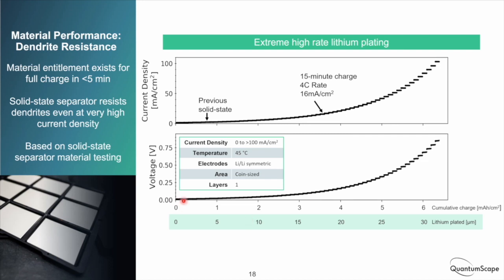And so this is showing the corresponding voltage that develops across this lithium-lithium cell. This test was done at 45 degrees because that's probably the condition most relevant to fast charge. I think for most fast charges, the car will already be driving, so the batteries will be somewhat warm, and they'll also heat up due to their internal resistance as you charge. So 45 degrees is a pretty relevant fast charge condition. We were doing this in a lithium-lithium configuration because a cathode really can't deliver this kind of current density. 100 milliamps per centimeter squared is just far north of what a cathode can sustain for long periods of time. So again, this is the materials level test.